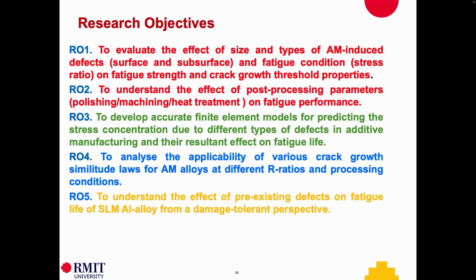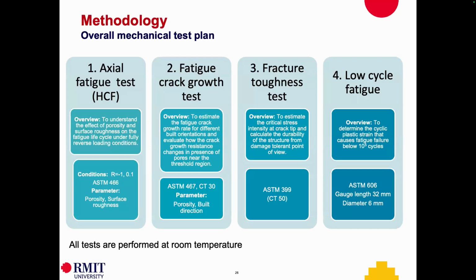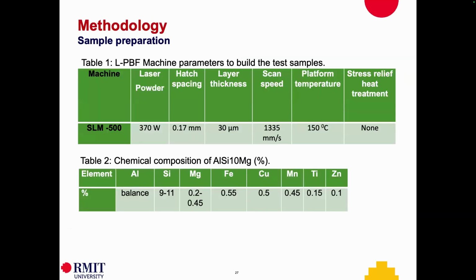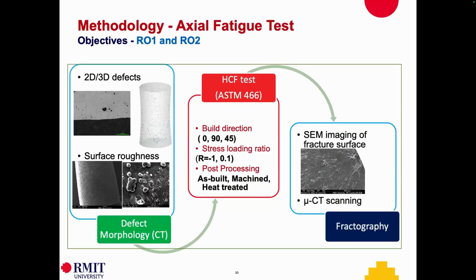And finally, we looked into what we call quick fatigue prediction for AM alloys using the so-called similitude laws, which are popular fatigue laws in the literature. You can relate different alloy properties. Based on one data set, you can develop another curve. So these are the methodologies, which we don't want to go through: high cycle fatigue test, fatigue crack growth test, fracture toughness test, and low cycle fatigue. And these are the material properties and the chemical composition which we used.